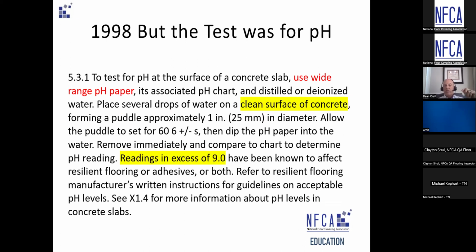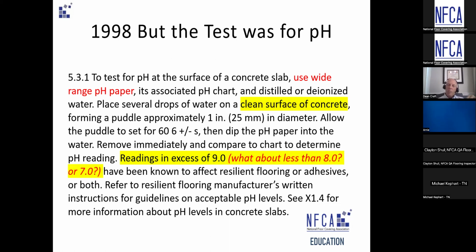The other thing too is it had an admonition or a warning, readings in excess of 9. But there was no mention, what about less than 8? What if the number went down? I mean, if you're expecting the pH of concrete to be 8, 9, or 10, and you test that surface and it's a 7 or a 6, that should be cluing you that something's not right, because the pH of the surface of concrete should not be that low.